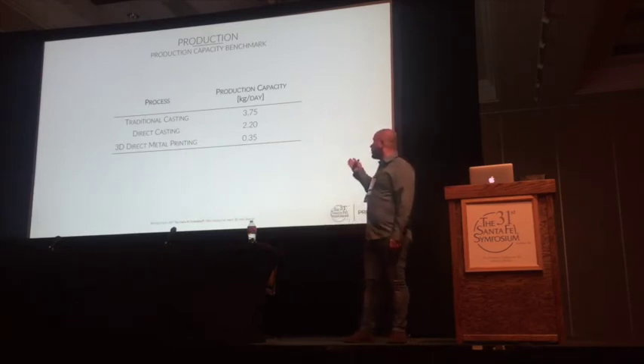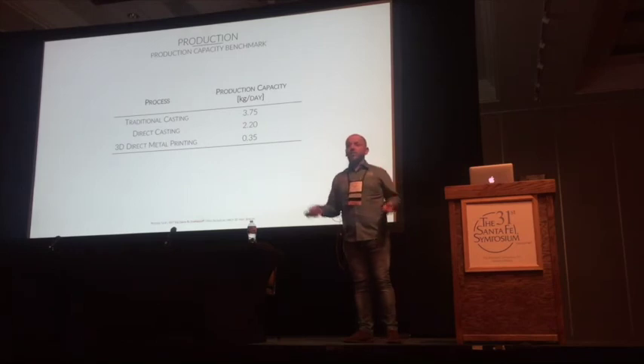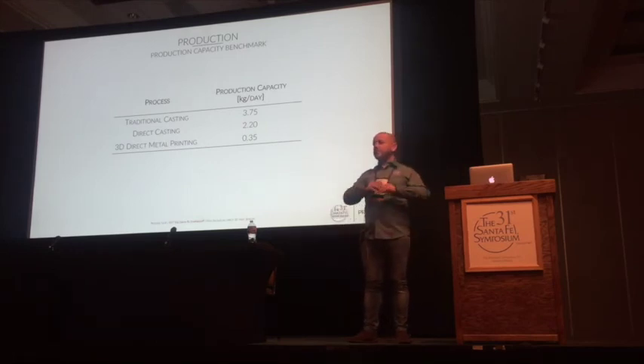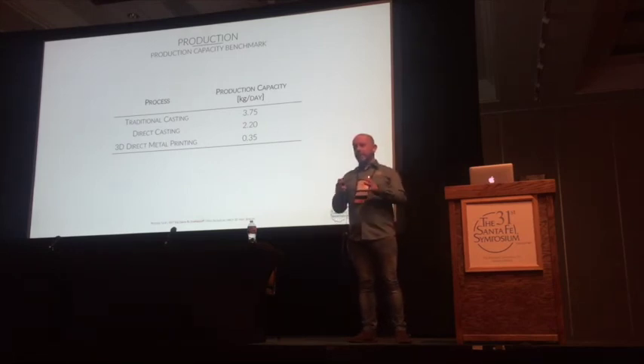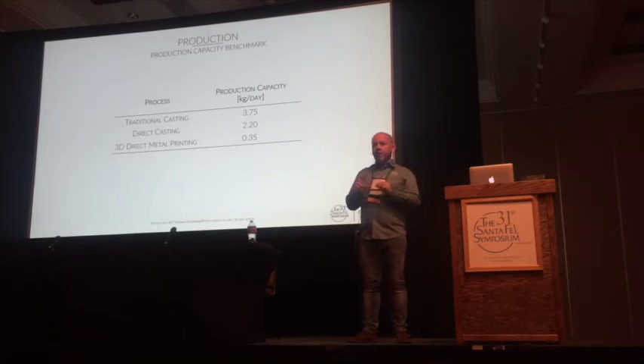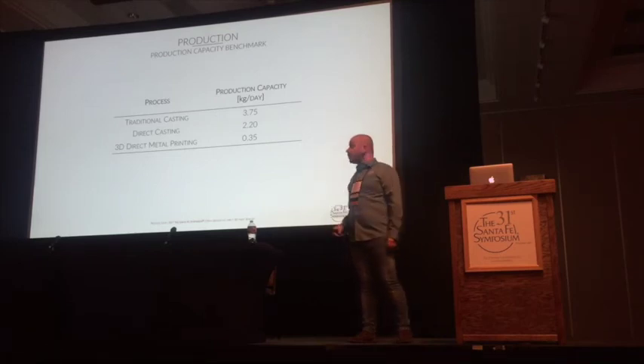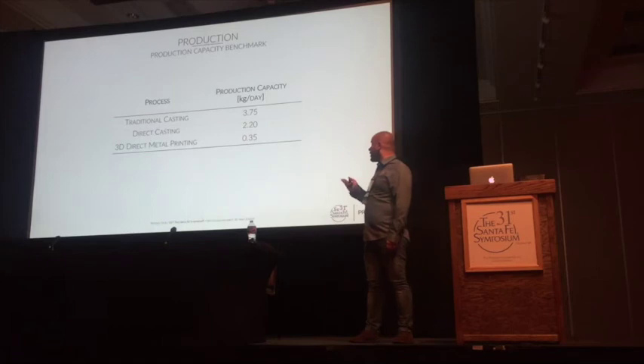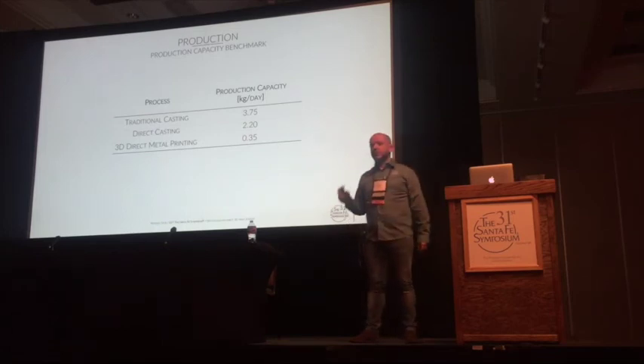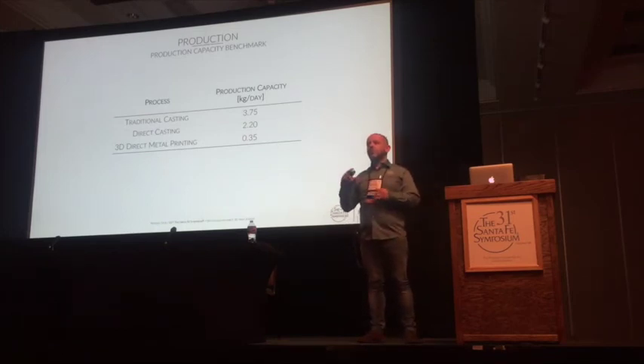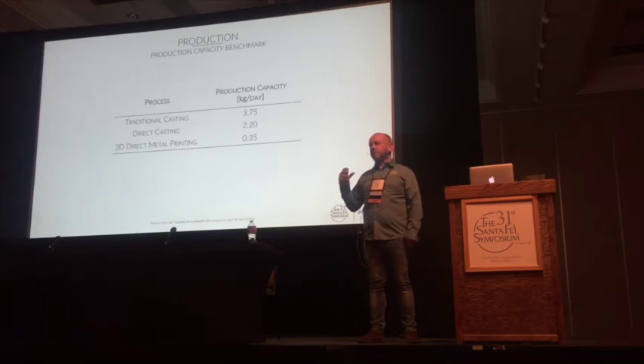So with the 3D metal printing, you can do no more than 350 grams a day. This is the maximum that you can do. And the part has to be quite particular to reach that volume. In case of traditional casting and direct casting, the quantity is much higher. So, from production point of view, they are much faster.